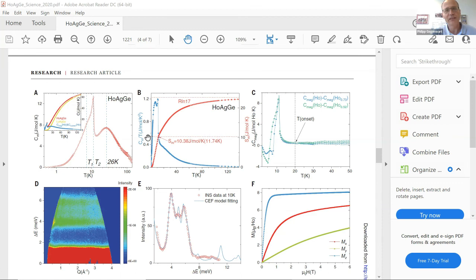and as I mentioned, only the 4 lowest singlets contribute to the magnetic order. So we have, I think, R log 4 collected at TN, and we need to measure up to much higher temperature to collect the full magnetic entropy. But I think we don't have clear indication for some missing entropy in this case. Although it's difficult to see because we have this large amount of total magnetic entropy available from the 10 4f electrons. Okay, thank you.